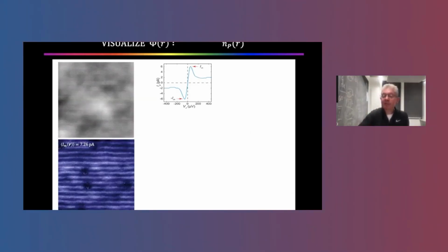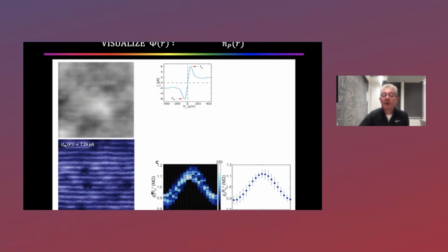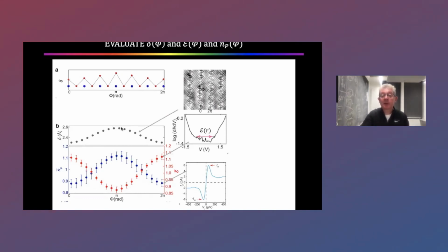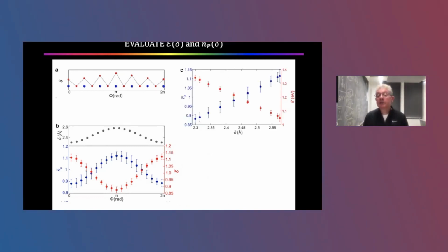Similarly, you can measure the Josephson current or the Josephson conductance. We had to measure the normal state junction resistance squared and multiply, make a 2D histogram, and then show this: the number density of pairs versus the phase of the modulation, measured. And the number density of pairs is changing by almost 20%. So this is the summary of the experiment. Find the phase from the topographic image, find the charge transfer energy in red from the gap in the spectrum, find the electron pair density in blue from the Josephson current, and label them all by the phase of the supermodulation.